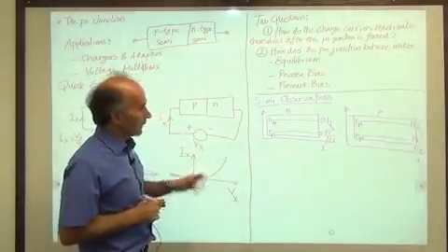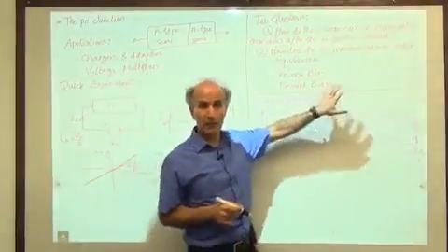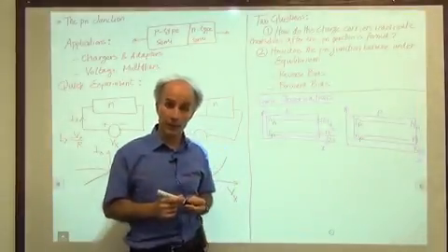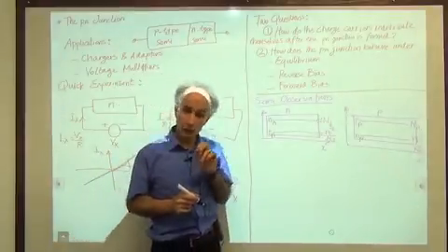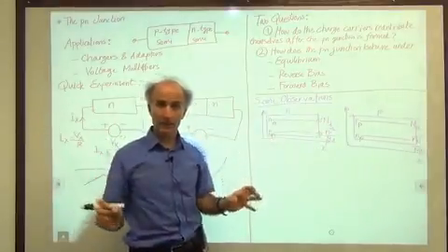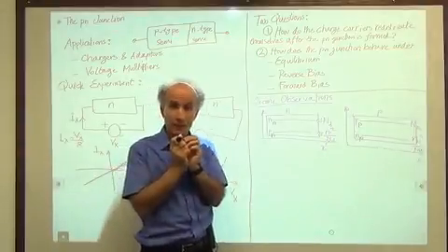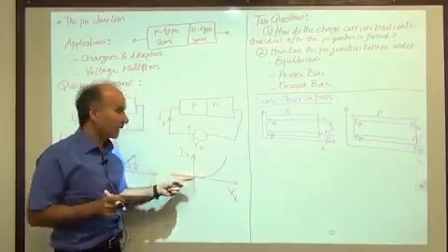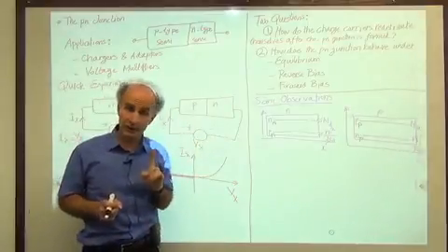Very well. So that is the situation when I bought a piece of N-type silicon and a piece of P-type silicon, and then I'm ready to attach them to form a p-n junction. Now, I should mention that if you do actually that, if somehow you go and buy a piece of p-type and a piece of n-type silicon and try to attach them, you will not have a p-n junction. Because for the p-n junction to behave as I mentioned before, this entire device has to be one single crystal.